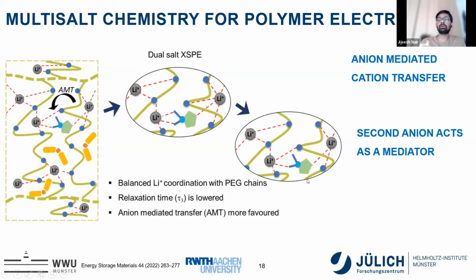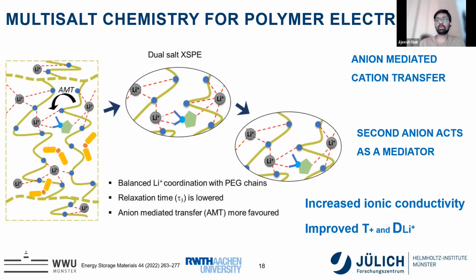Because of the coordination, for example, in a PEO-based system, lithium is coordinated to PEO. When it is coordinated more to the PO, it will stay there. It will not move because it needs higher energy to move. So it reduces the ionic conductivity. So when you are adding the second anion, this lithium is less coordinated with the PO and more coordinated partially with the anion. This gives the lithium a lower relaxation time. The relaxation time means the amount of time that lithium is staying with that particular polymer chain or particular space. This is reduced drastically, and this anion can be a carrier or a mediator to transfer this. So because of this, we get increased ionic conductivity, improved transference number, improved diffusion coefficient, etc.